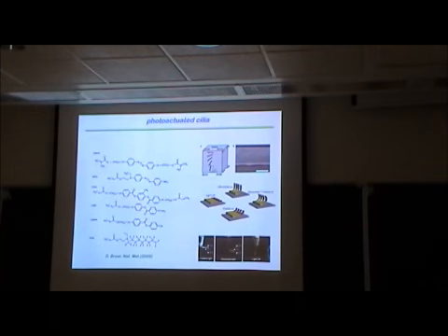So this is the nematic liquid. Then you photopolymerize these acrylate groups, since there are terminal acrylates on these molecules. This mixture forms a nematic polymer network. So now it's a solid material with this nematic deformation built in.